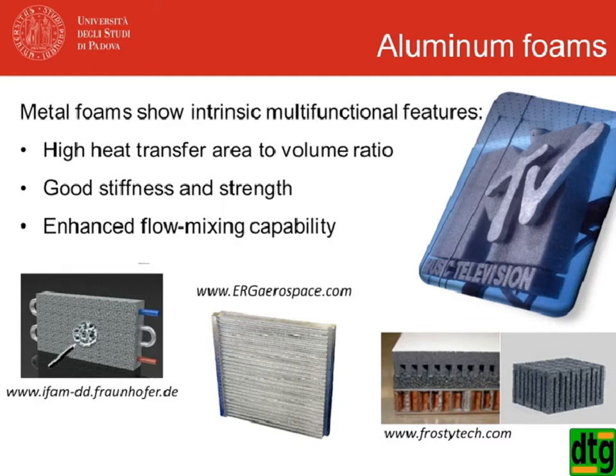Metal foams show intrinsic multifunctional features: high heat transfer area to volume ratio, good stiffness and strength, so we can prepare sandwiches with aluminum foams inside, or metal foams if you want, and obtain a very strong mechanical part. And of course, the tortuous path enhances the flow mixing capability. This is important in active heat transfer. In the present application, so in the solid-liquid phase change, it is not that important. However, the flow mixing capability can be seen as heat transfer capability.